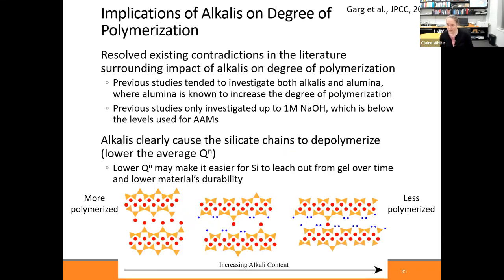I've essentially said this already, but it's the degree of polymerization that's very important. And so what we found was that as you add sodium to the system, alkalis, it causes the silicate chains to depolymerize. This might be of a concern because the lower coordinated these silicate units are with each other, it's likely easier for the silica to dissolve over time in aggressive environments. But on the flip side, we know that aluminium increases this degree of polymerization, makes it more polymerized. And so that's a good